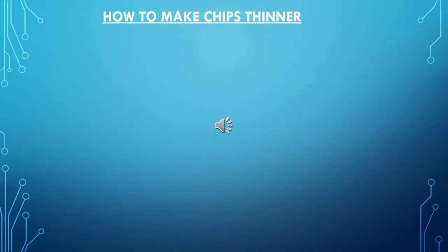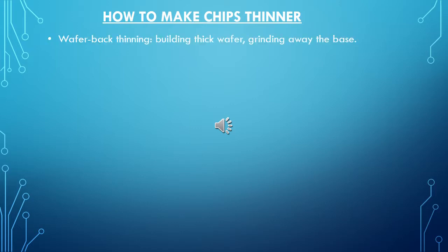Now, we will see how we can make these chips thinner. The most straightforward way is to make a conventional silicon chip and grind away the base. This can be done after the circuits are drawn on wafers and before they are diced into chips. Another way is to build a thin film of silicon on a layer of oxide which lies on a thick silicon substrate. These are called silicon on insulator wafers. The silicon is then removed selectively and uniformly.